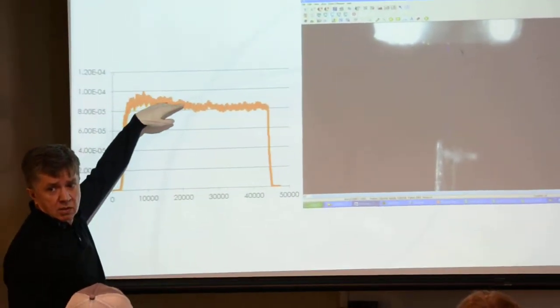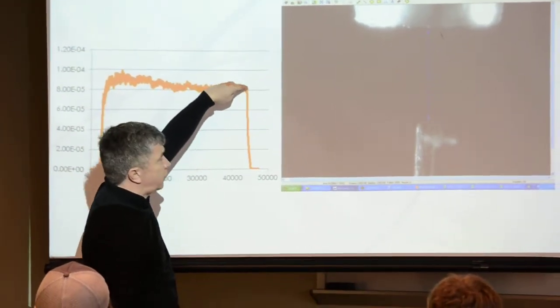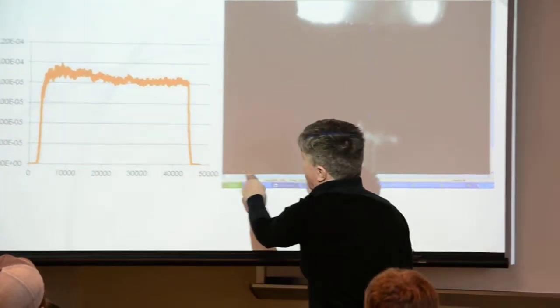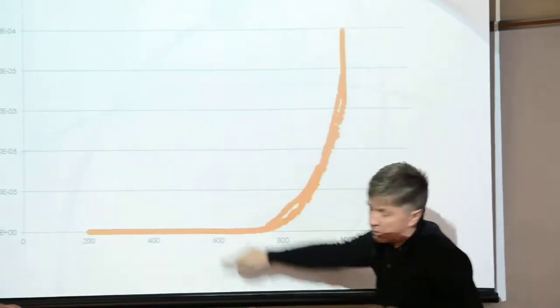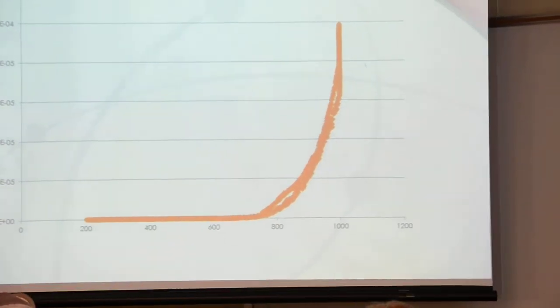We tried to put a few of them close to each other. Thinking if you put three, you should get three times what you get with one. As I looked at them, I saw them forming like a bouquet, physically bending toward each other. It's tough to reach 100 microamps. Furthermore, remember this is going up. There may be 1000 tubes contributing. You stay there, start burning some, they degrade. When you end up, instead of 1000, you get 945. Some have burned. As you sweep down, you don't expect the IV curve to be the same going up and down. You expect to see hysteresis.